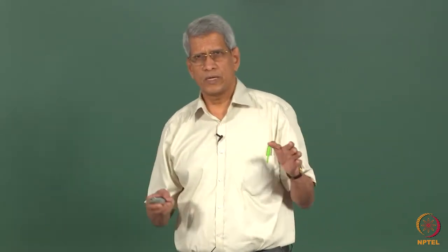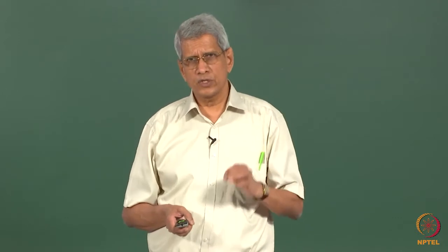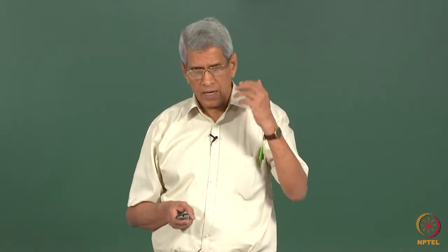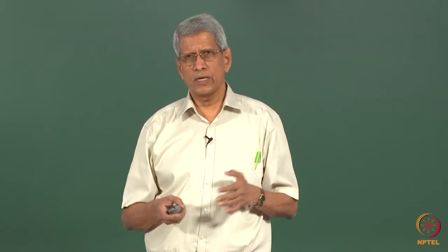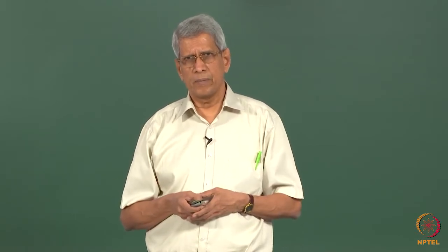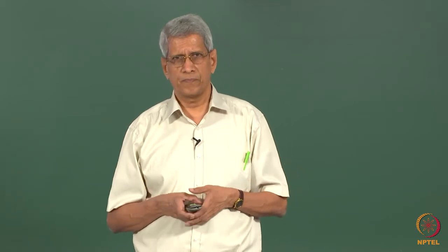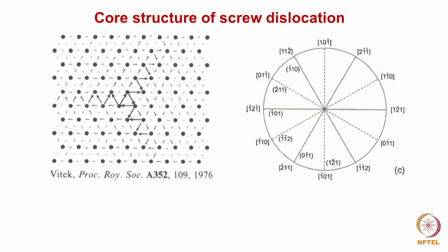So far we considered faulting. Now let us look at the core structure of the dislocation itself. A lot of simulation work has been done to look at how the core of a perfect dislocation looks in BCC. This is from the work of Vitek. Essentially the dislocation line, or the Burgers vector, comes out of the screen, perpendicular to the screen. The atom positions being shown on the screen are on a 110 type plane. The Burgers vector is perpendicular to it.